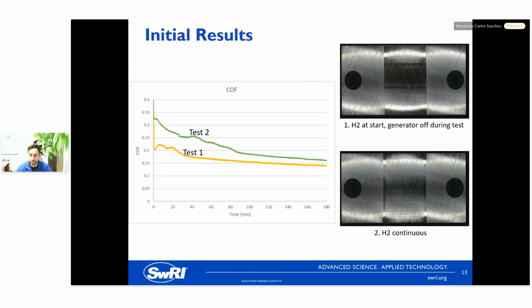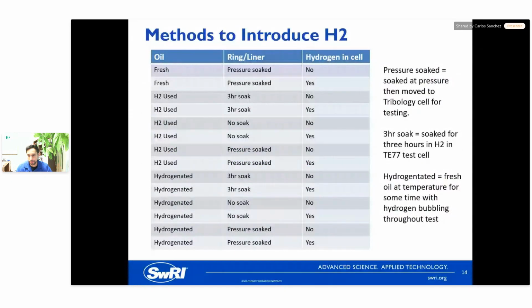Whereas if you have it continuously flowing throughout your test, where you have the hydrogen actually flowing inside the chamber throughout this test here, you get more of an effect on friction performance. But throughout this test program, we looked at different methods in which to introduce hydrogen and whether it actually has an effect on these engine parts or not. So here's just a list of the different things that we did to see how well it would affect it or not.